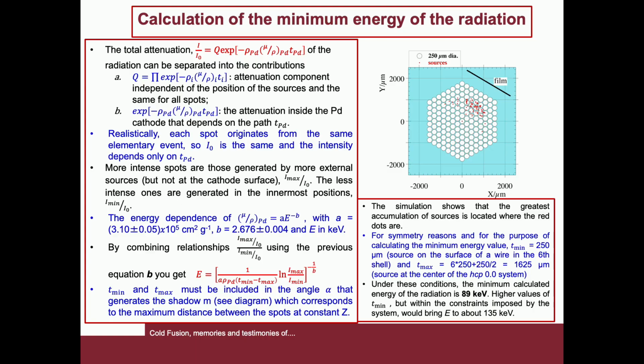The simulation shows that the greatest accumulation of sources is located where the red points are. As we have seen previously, for symmetry reasons, in order to calculate the minimum energy value, we set t minimum equal to 250 microns. This means that the source is on the surface of a wire in the sixth shell. It is in the outermost shell, but not in the last.